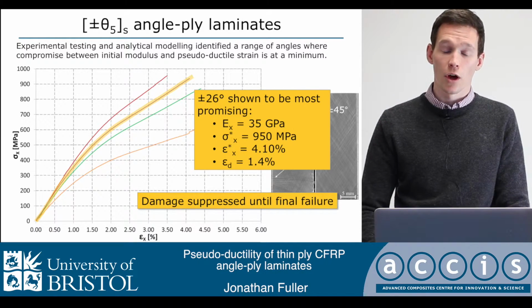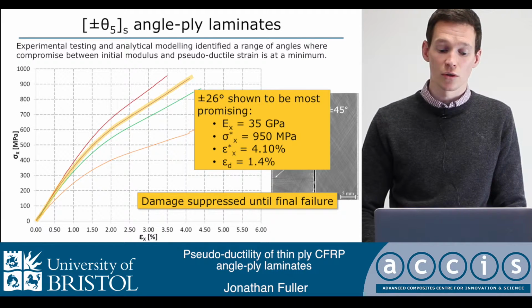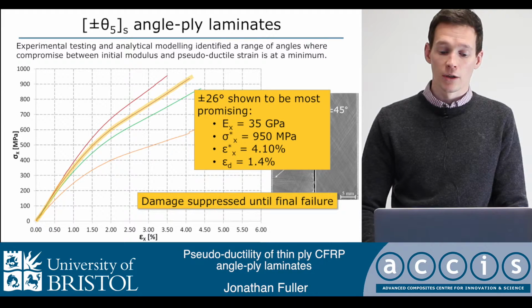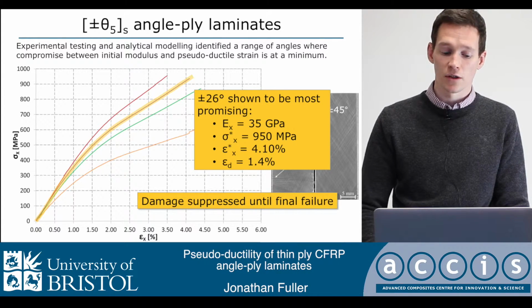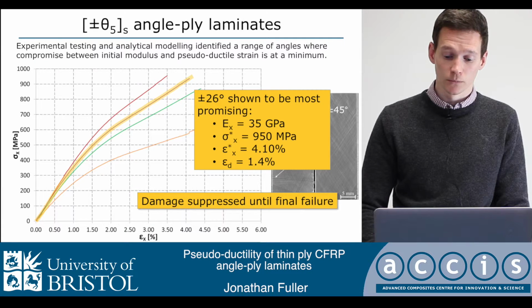So homing in on a particular configuration, I chose plus or minus 26 degrees, and you can see here Young's modulus is 35 gigapascals and the strength is 950 megapascals. And then the epsilon D at the bottom there of 1.4%, that's the pseudo-ductile strain, which is very promising.